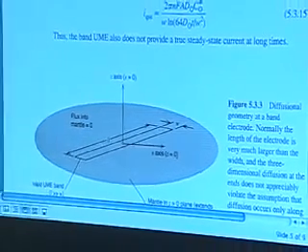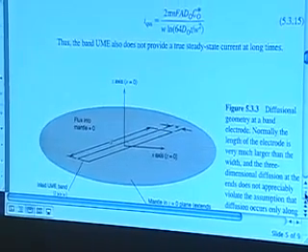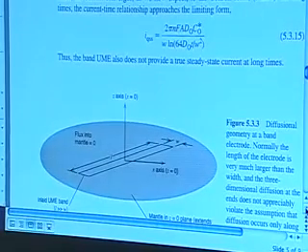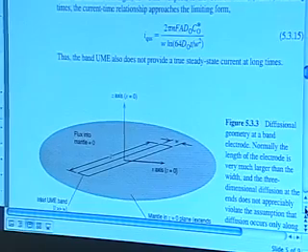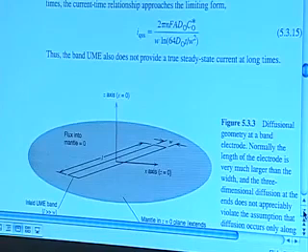The way you would make a band is either lithographically write down a metal line on an insulating substrate like gold on glass that you would mask and make a micron or less and make it very long so you don't have edge effects to worry about. Or another way is you evaporate, say, gold onto a piece of glass and then evaporate something else insulating on top of that. And the way Henry White has done this at Utah is then you just break it in half and you put the edge in a solution, and now the solution sees that line of metal sandwiched by two insulating things.